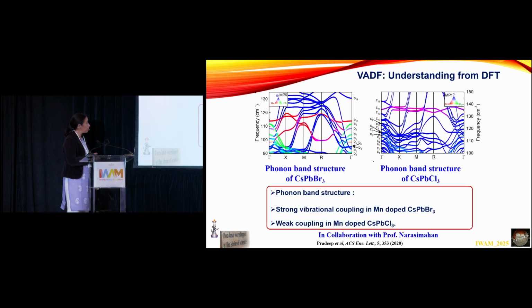So for that, we looked at the phonon band structure, and you see that at the gamma point, specifically for the cesium lead bromide, instead of having just blue, green, or red as it should be, there is a whole range of colors over here, suggesting that there is a strong interaction. The same is true for chloride, but much weaker. You can see just a small light blue instead of a whole range of colors. So basically, there is strong vibrational coupling for the manganese doping in cesium lead bromide, weak coupling in manganese doped cesium lead chloride. So theoretically, we see that it is indeed possible.